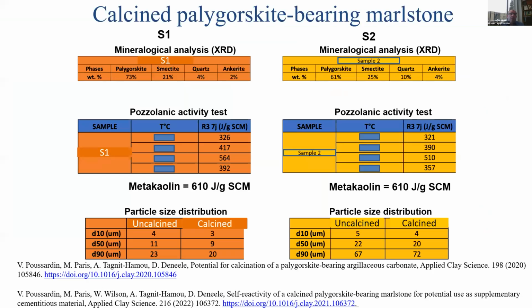We spoke this morning about North America, and this is the calcined clay that we found in the US, and the amounts are also very large, but this is what we call the Palygorskite. So it's not kaolin, but it's having very good reactivity, as you can see by the pozzolanic activity test here.